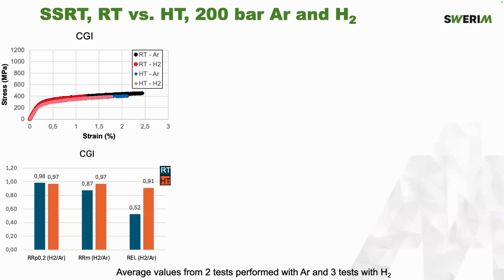Digging into the first results, here we have representative stress strain curves obtained at room temperature and high temperature in argon and hydrogen. Below that, you have the relative properties, namely the yield strength, tensile strength, and the relative elongation, comparing hydrogen over argon. What one can conclude from this is that all the properties seem to be affected, but the most severe one is the elongation. And if we compare the effect of temperature, we see higher degradation at room temperature compared to high temperature.